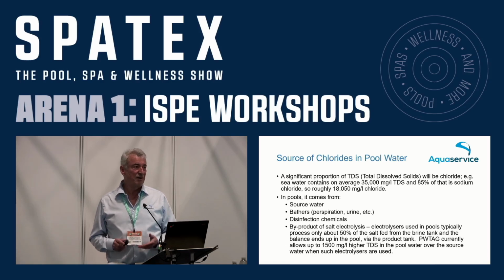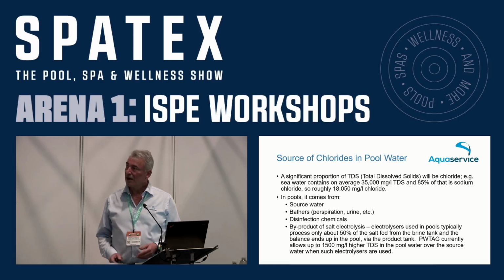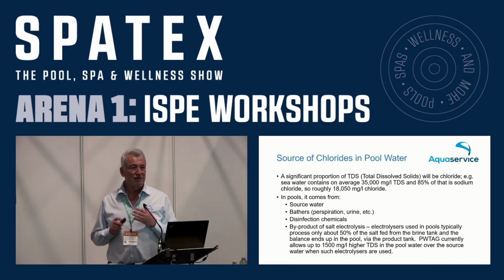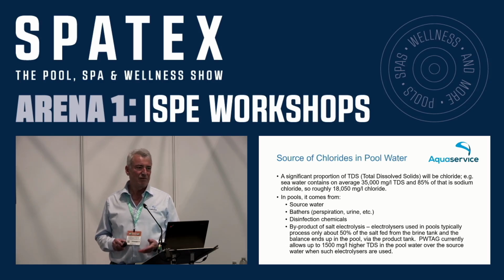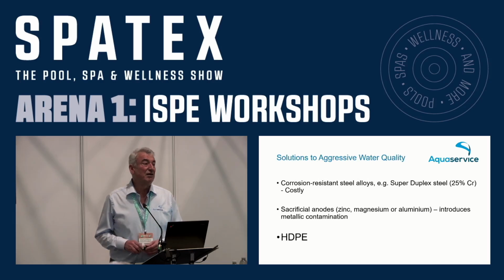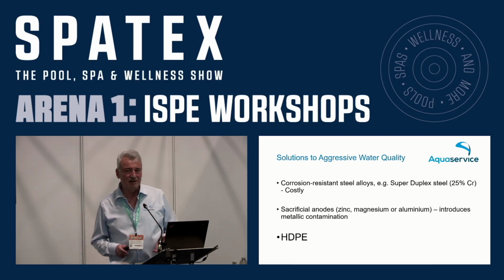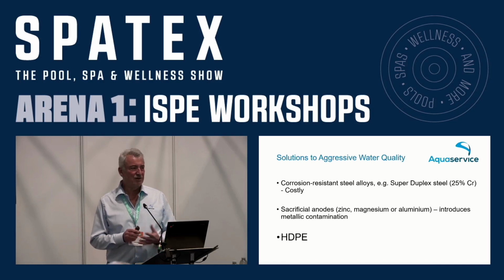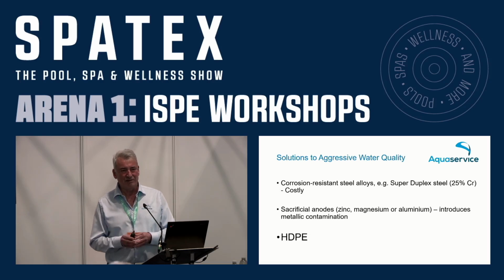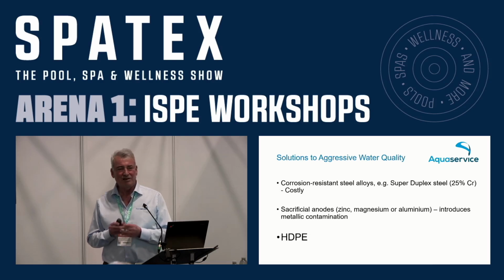And I expect, because of the increasing popularity of these electrolyzers, against which I don't make any derogatory comment, it's just a fact, they are here, but it's also a fact that they introduce salt into pool water. And unless that pool operator dilutes rigorously enough to keep the TDS in the pool water below PWTAG recommended limits, there will be more and more cases of crevice corrosion happening. As I said a while back, a lot of manufacturers are aware of these issues. It's not because they are supplying an inferior grade of 316L stainless steel or that the products are defective. It's because the material itself is just not capable of withstanding attack by chlorides at the sort of temperatures that we see in swimming pools.